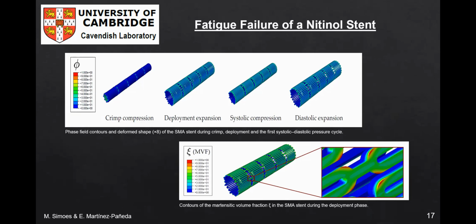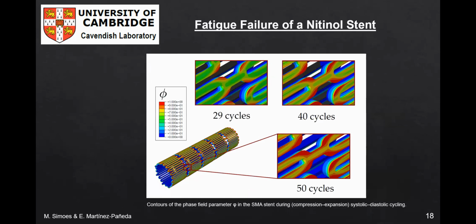The figure at the top shows the deformed shape of the model during the 4 stages of the analysis, the crimp and expansion stages of the deployment phase, and the systolic compression and diastolic expansion stages associated with each pressure cycle. A significant amount of damage occurs during deployment, but no cracking is observed. This is also the case for the phase transformation. Most of it takes place during the deployment phase. In the bottom figure, the contours of martensitic volume fraction at the end of the crimp expansion deployment process are shown. The martensite volume fraction contours show that the martensite phase is localized in the edges of the stent struts. This is also the location where cracking initiates.